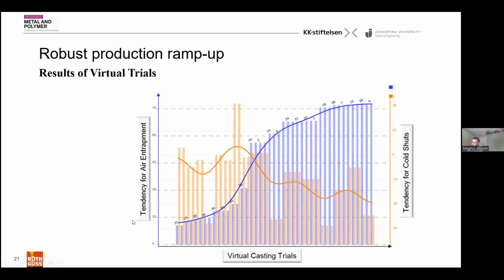I mean, this is just showing on the blue axis the tendency of air entrapment. These are the different designs. On this yellow or orange axis, you have the tendency of cold shuts. You can see that, for instance, there are quite many experiments where you have a big tendency for air entrapment. So here you have lots of trapped air. These designs 12, 26, and 5, for instance. Then you have a few of them which really give a high risk for cold shuts. And then, of course, there are some good designs as well. Here you can find at least 2 or 3 designs which have both low risk for cold shuts and low risk for air entrapment. So this is simple screening by running 64 simulations without doing too much analysis. You can find out something which will improve your production.